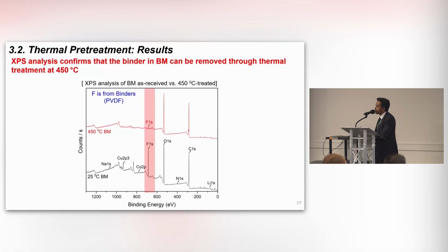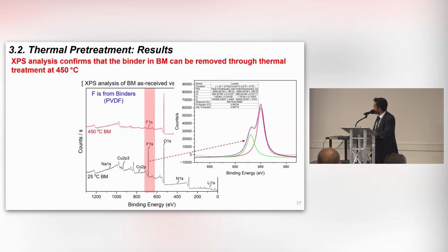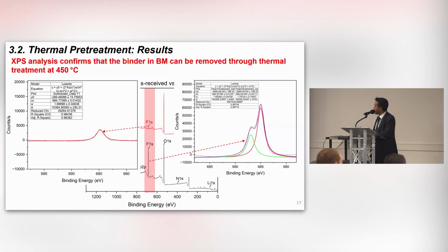However, in order to verify our hypothesis, we have performed XPS analysis. As you know, most of the binders are PVDF. So we checked the fluoride in the room temperature black mass and the 450-degree black mass. You can see the fluoride is significantly high at room temperature, and it significantly decreases when we increase the temperature. This fluoride is related to the PVDF, and also some fluorides are connected with some critical metals such as lithium. So after the temperature increase, most of the PVDF is eliminated, but some small amount of fluoride remains, associated with some critical metals.